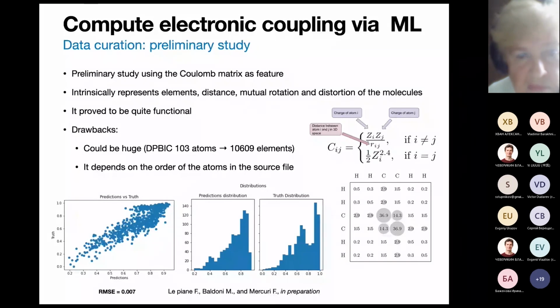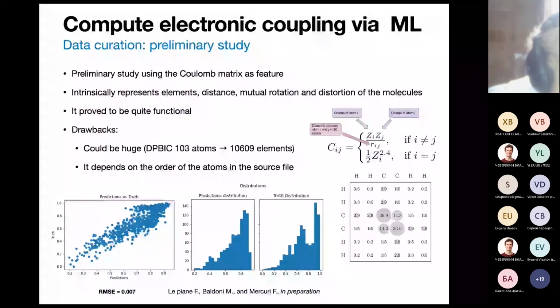This representation could be huge, even for a small molecule. The DPBIC molecule, the test molecule I've shown you before, has around 100 atoms, but the relative Coulomb matrix has more than 10,000 elements, so it's quite heavy. And again, the Coulomb matrix depends on the order of the atoms in the source file. This is very bad for the transferability of this data structure.